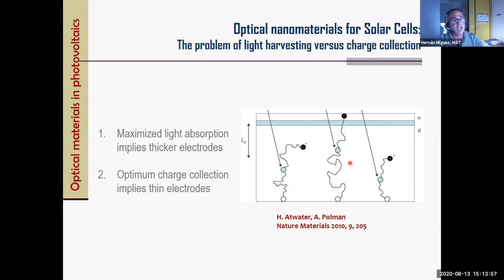But if I do that, I'm forcing charges to travel very long distances. And when they travel very long distances, they can recombine and you can lose them. So there's always this compromise, right? You need to absorb light efficiently, but at the same time collect the charges efficiently. And this is why the optical design of a cell is so important, because you always want maximum absorption in the minimum thickness possible, right?